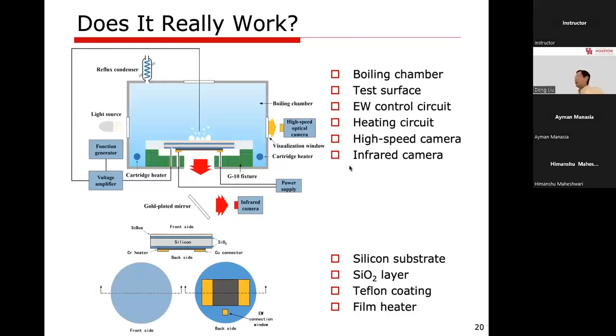So for that purpose, we constructed this experimental apparatus. So we have a boiling chamber made of aluminum. So inside, the key part is the electrowetting piece. It is made of 3-inch silicon wafer. I will not go through all the details, but we use silicon itself as the electrode, because it's very conductive, to generate the electrowetting signal. And also at the backside, we deposit the chromium thin film heater, because for boiling you need the power input. So that is coming from the heater.